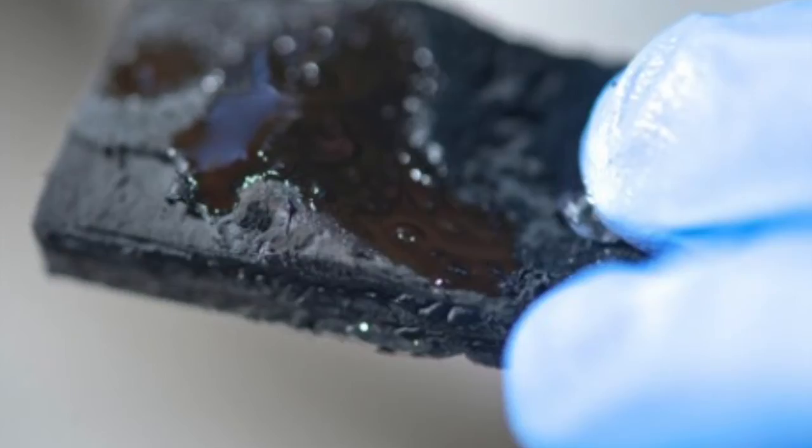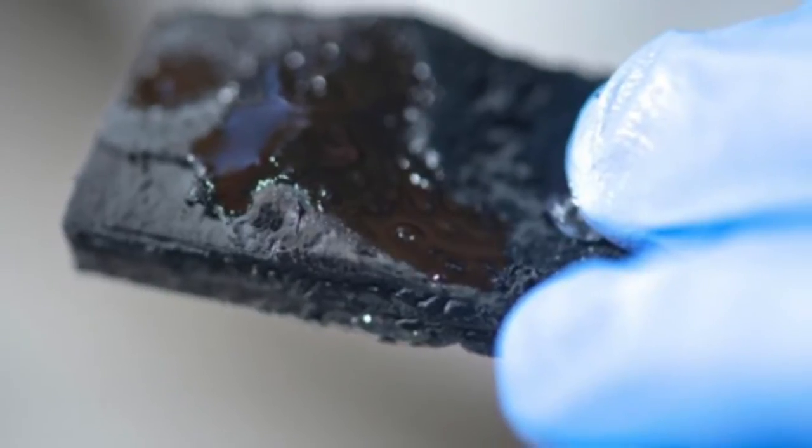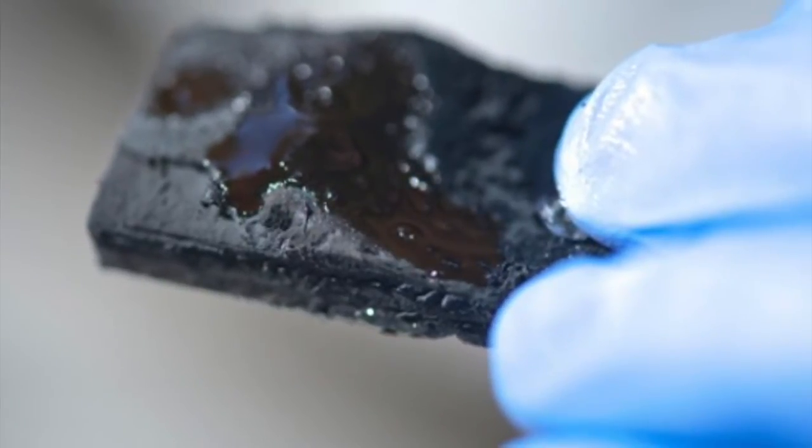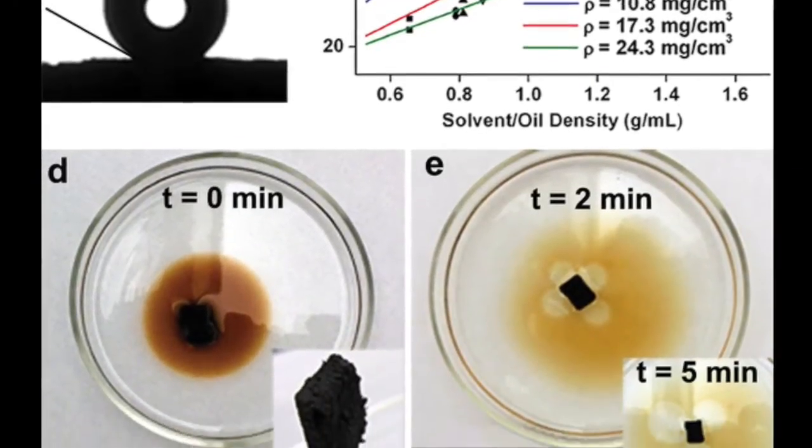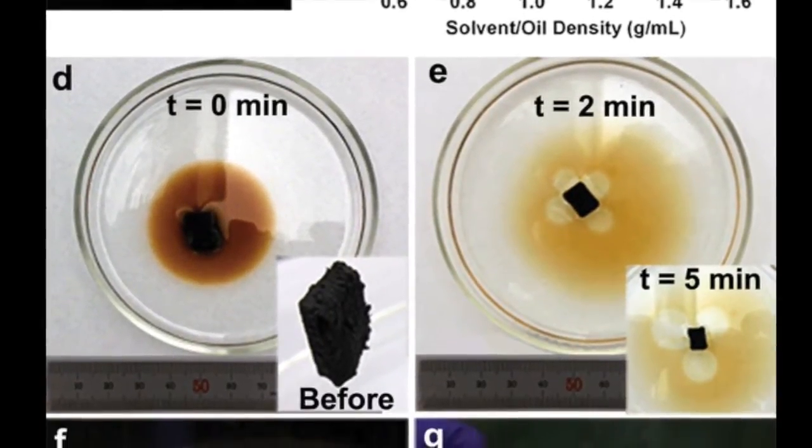Exploiting the many properties of the boron-doped carbon nanotube sponges, such as being hydrophobic, light, porous, highly elastic, and reusable, this material is an extremely effective absorbent in cleaning up oil spills. Studies have shown that the sponges are able to absorb oil up to 150 times their initial weight without absorbing water.